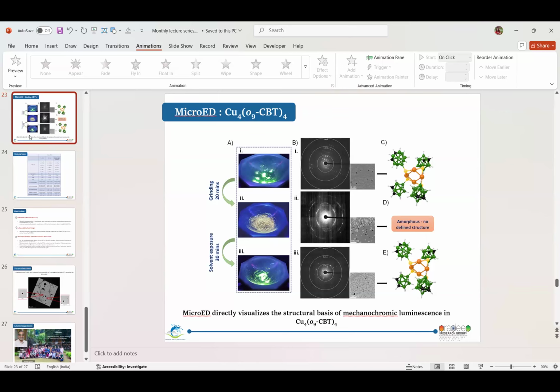You can see the amorphous nature. That is why she is not talking about that. She is talking about the extent of order. Yes, she is talking about, let us say there is orientational disorder in this system. She is enhancing the translational order and reducing the orientational disorder, which requires very little change.